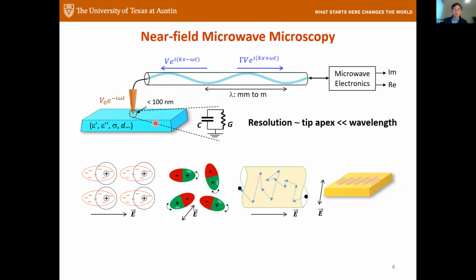So roughly speaking, the two channels will show something like this. This one is proportional to capacitance. As the material gets more and more conductive, the capacitance goes from a small capacitance to a large capacitance. So the imaginary part goes up monotonically, and then there is a lossy region somewhere in between. And after this, the loss goes downward. And you do the inverse of this. This is about a mega ohm per square, right?